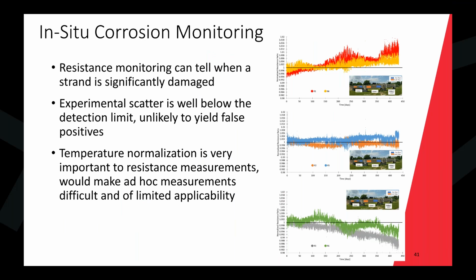And the real finding we had is the scatter due to the temperature is large enough that if you weren't doing a continuous monitoring scheme over a period of years, it'd be very difficult to tell, if I made a resistivity measurement on a strand, whether it's fully connected or not. Rather, how much corrosion damage had occurred could be confused with temperature variations. So this technique, while interesting academically, as an ad hoc measurement to see if the strand is corroded or not, you're not going to get much of a response.